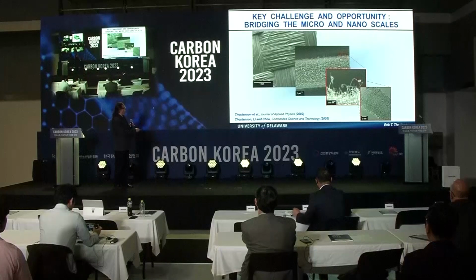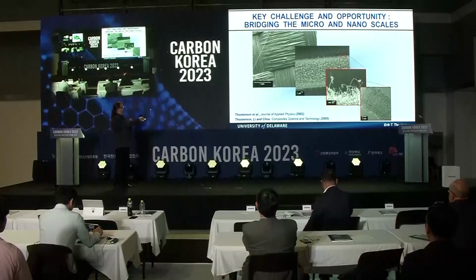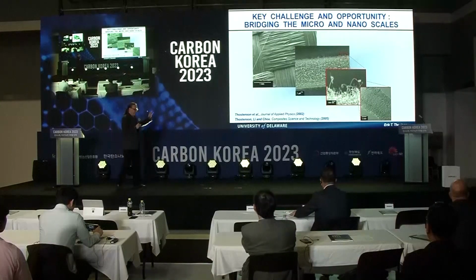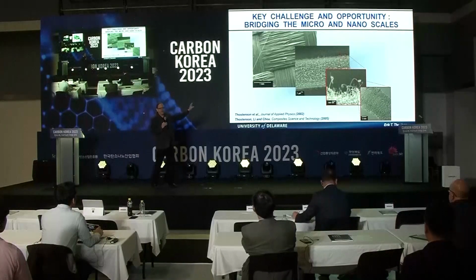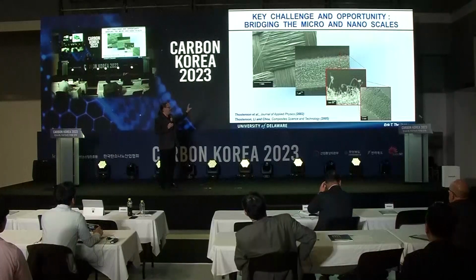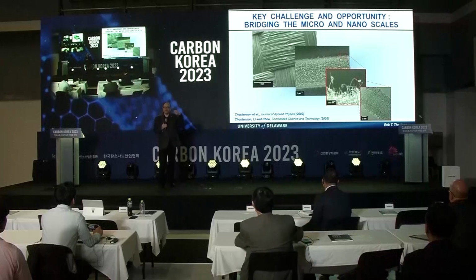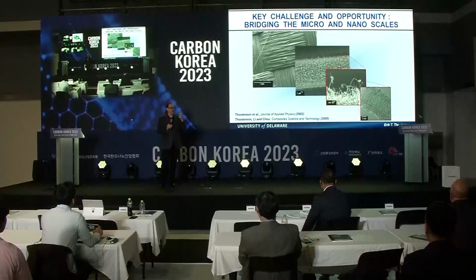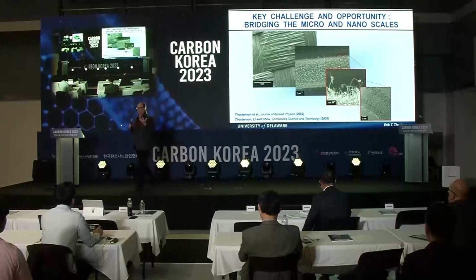What you see here in the middle is a single carbon fiber that is about 7 microns in diameter, where we've grown carbon nanotubes on the surface. And what I like to call this is a multi-scale hybrid composite, because we're not just combining different types of reinforcements, but we're combining different reinforcement scales, scales that are 3 orders of magnitude smaller.